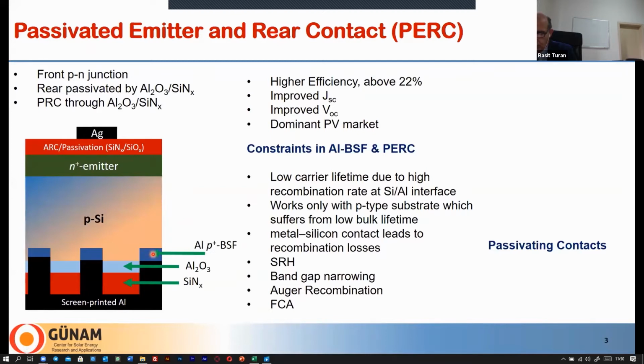And this cell demonstrated higher efficiencies, well above 22%, because this cell can have improved short circuit current density, thanks to the optimized back reflector by aluminum oxide and silicon nitride. It has also improved VOC because now the aluminum back surface field is local and most of the rear side is being passivated. And now this PERC technology dominates the PV market right now.